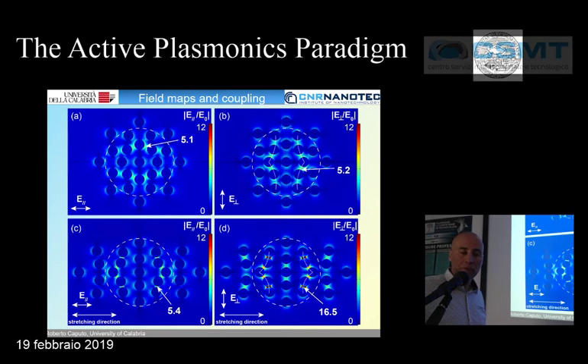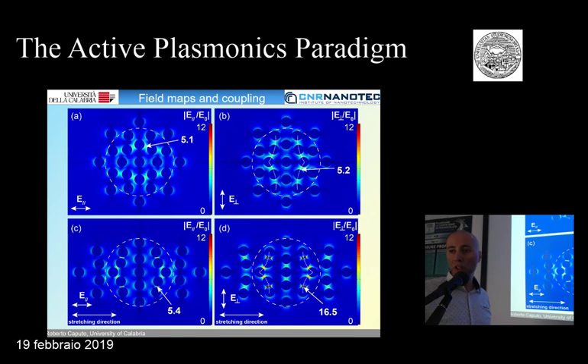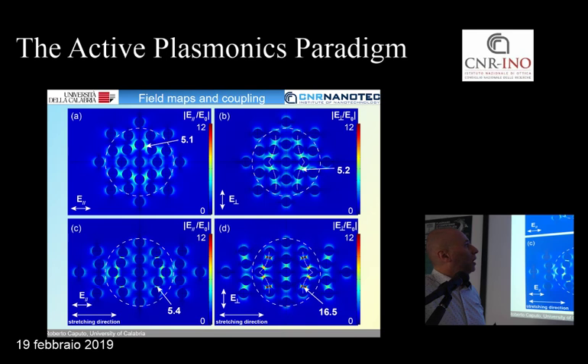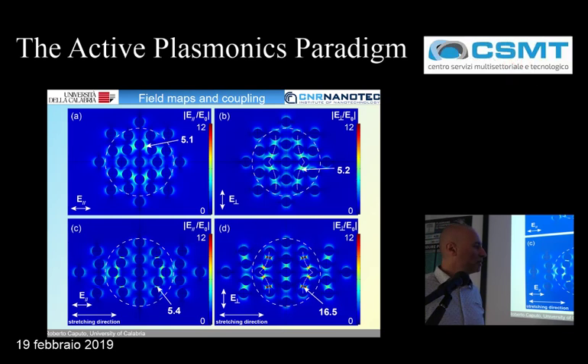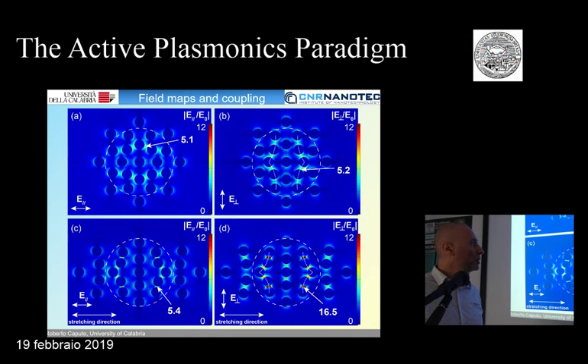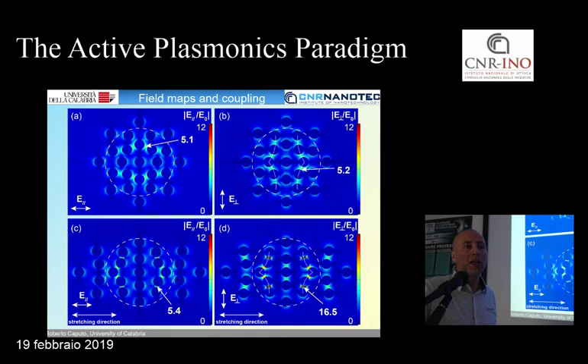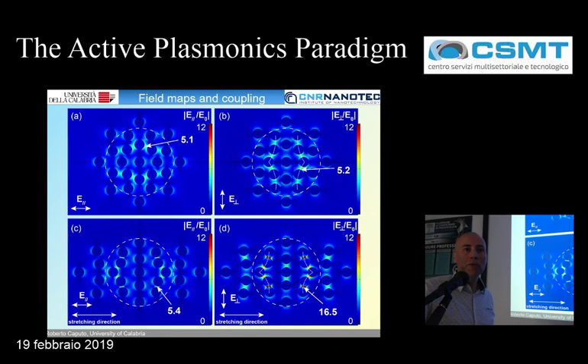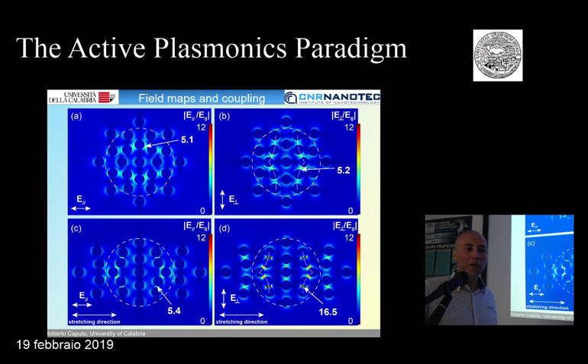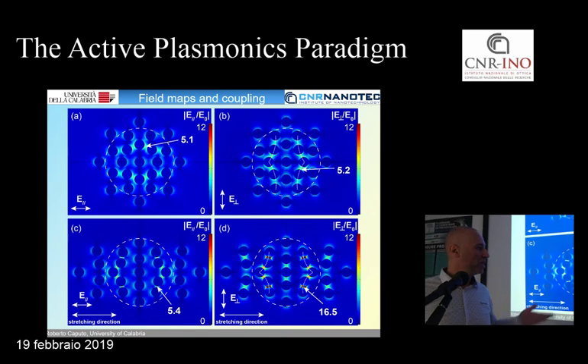When we consider the field maps of the system at rest and under stretching for the different polarizations, you can see that indeed there is a very similar field, of course, at rest, but the situation is much different when you consider instead the stretched configuration. With the polarization along the stretching, we obtain a value which is quite similar to the original one at rest. And in the perpendicular direction, we obtain a value which is about three times the original one. This is to say that what we observed experimentally, that the change of extinction cross-section of the system is negligible when you consider the polarization along the stretching, and very different when you consider the polarization perpendicular, is confirmed also numerically.